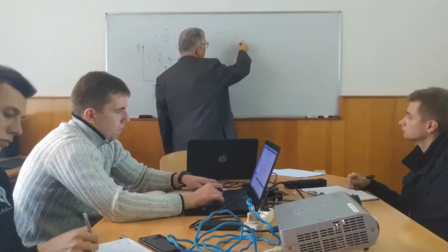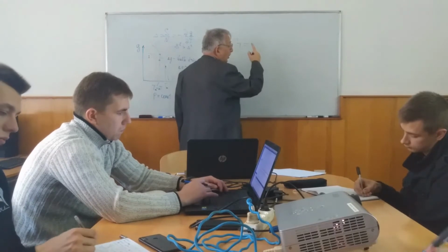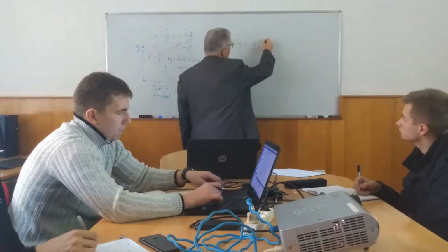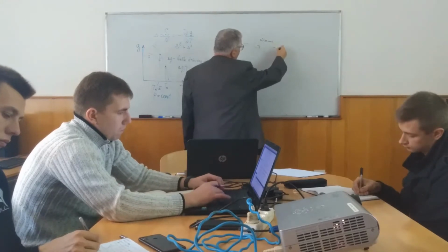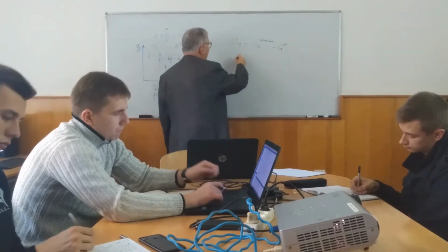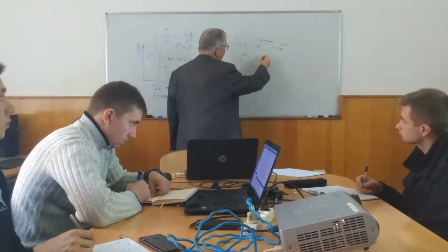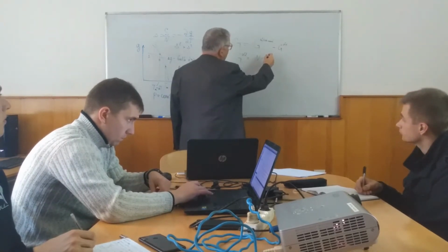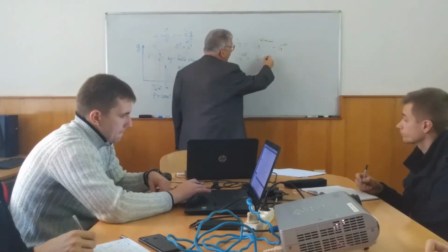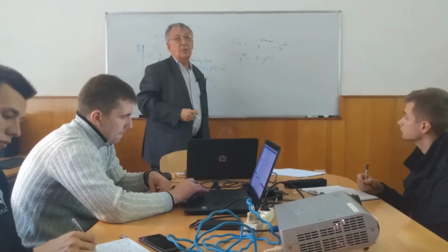In this case, we consider the change delta G. We consider the change of total Gibbs free energy when we have the nucleation of one nucleus. So this is G after nucleation minus G old. G old is equal to N multiplied by GL, because the old state was pure liquid. Before nucleation we had only liquid, so GL as a function of T. N is the total number of atoms in the system.